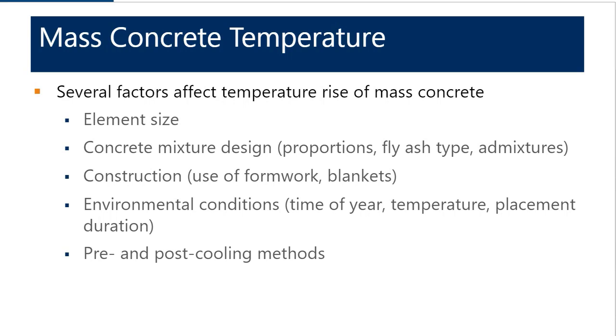If you're placing in warm months, you might have a greater potential for temperature rise, but if you're placing in cooler months, you may have a greater potential for thermal differentials or thermal gradients that might cause cracking. It'll also include things like the temperature of the concrete when it's placed, how long it takes to place the concrete. And then there's also pre and post cooling methods that you can use to help control the temperatures of the concrete, either before it's being placed or after it's being placed. And we'll talk about each of these. But all of these factors influence the potential temperature rise in a mass concrete placement.